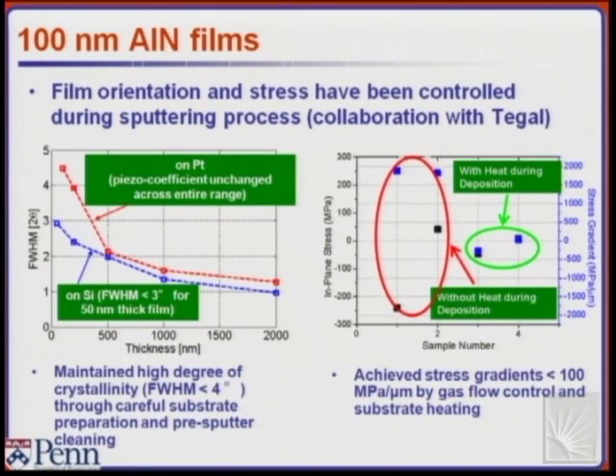So the key challenge is actually miniaturizing those films, and when you deal with those films, maintaining the quality of the piezoelectric element. Depositing a 50 nanometer film is not a big deal, but making it piezoelectric is another story. So what we do so far is monitor the full width at half maximum, which is basically a measure of how well-oriented the material is. Below 2 degrees, we consider to have a very good piezoelectric material. Below 5 is still a piezoelectric. It will not work very well probably for a high Q resonator, but will still work for a mechanical actuator. At least that's what we've seen in correlation in experiments, based on data on full width at half maximum and experimental data on mechanical resonators and switches.